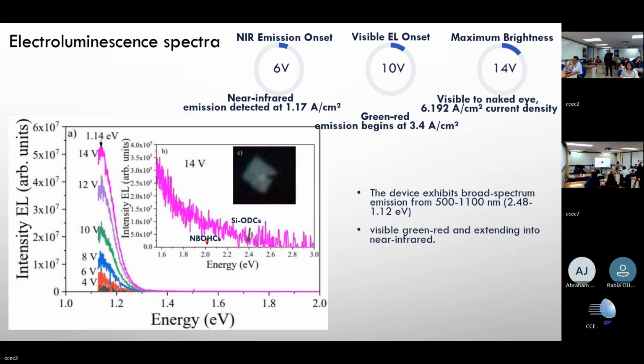We can observe that near infrared emission is detected from 6 volts, and this increases to 14 volts. Well, the visible emission is in this direction. This visible emission could be related to red and green, and is associated with silicon oxide deficient centers and non-bridging oxygen hole centers, and the infrared electroluminescence is associated with defective levels.